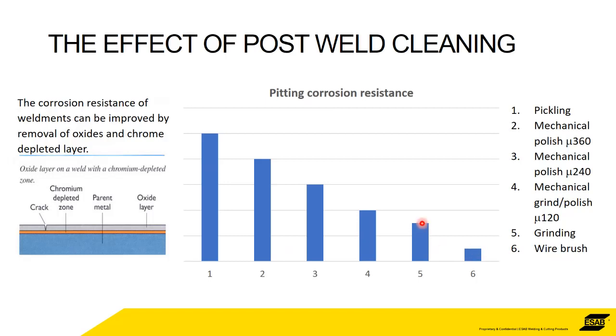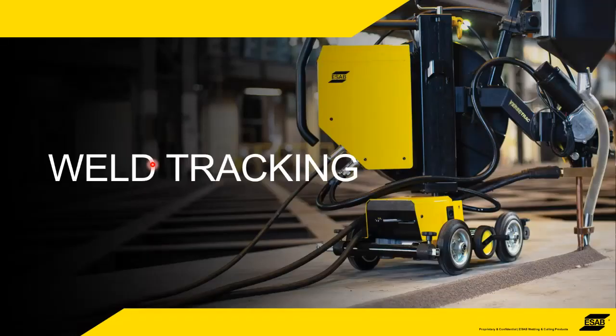If you grind it and get a bit better surface on it, then you can see the resistance is 3 times, 4 times better than with a wire brush. 4, 3, and 2 are mechanical polishing with progressively finer grain abrasives. So the finer you get, the more highly polished it gets, the more resistance to pitting it has. And then ultimately, the best that you can achieve is by, number one, pickling and passivating. Then on this scale, you can see it's a good 10, 15 times more effective at increasing the pitting corrosion resistance. That's what I've got to say on WPSs and the importance of that.